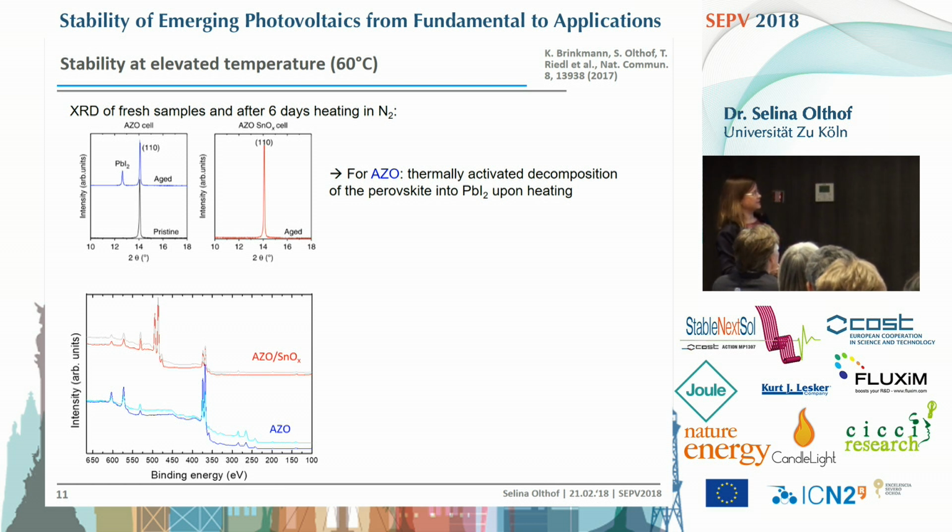It just stays intact. Down here in the XPS measurements, so this is again fresh device and aged device of both these stacks, you don't see the iodide appearing. So again, it tells us a very different degradation process. No iodine on the surface.